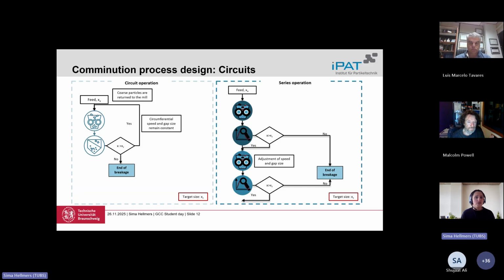And the other approach was a series of operations. That is, we had a feed, and we set the gap size. We ground the material, but we did not sieve. We just analyzed the particle size distribution and adjusted the gap size and speed based on this new product, and then adjusted several times until the whole material that was in the system reached the desired particle size.